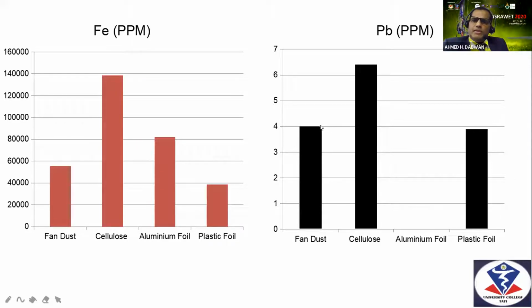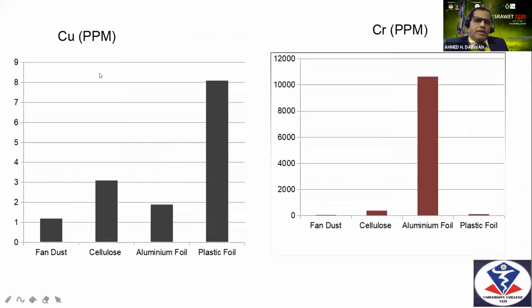For lead, this is parts per million, not very high, but for cellulose, fan dust and aluminum foil it's almost 0. Plastic foil somehow 4. So if you take the average, around 3 parts per million. For copper, the average will be about 3 or 2.5 parts per million. For chromium, also used in the steel industry, we found it's a little bit high compared to the others. The average will be 2,000 something. So this is for heavy metals from dust collected in the UC campus.